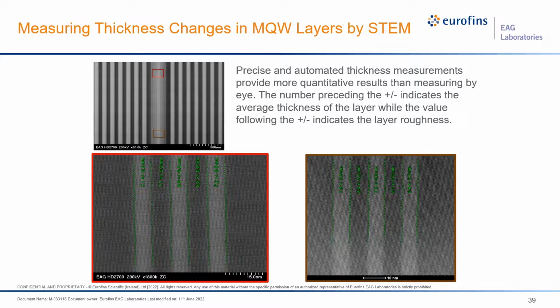STEM EDS line scans can also be used to evaluate the thickness uniformity in the multi-quantum well layer across the device. The image at the top shows two regions from which higher resolution images below were taken. The layer thicknesses and error bars are shown in green, and I'm sorry if they're hard to read. The error of 0.2 nanometers suggests that there are no thickness differences in the high Z, those are the lighter layers, but there is in the low Z or darker layers.